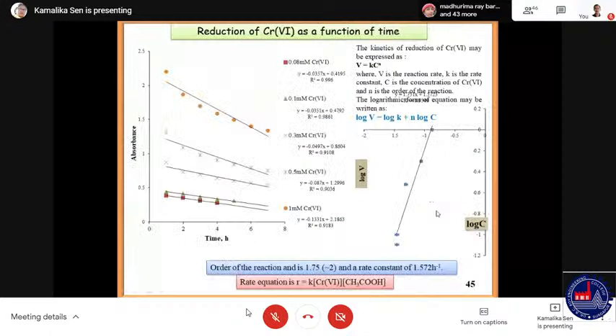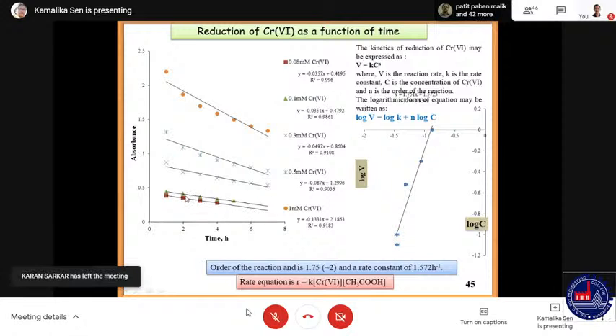Here we have tried to find out a rate equation where with increasing concentration of chromium 6, we have plotted different time scans. So if this is with 1 millimolar chromium 6, this is with 0.5 millimolar, this is with 0.3 millimolar, and so on. So we can see that the rate is decreasing with decreasing concentration of chromium, and if we plot the log of the rate with log of the concentration of chromium, we get a plot like this.